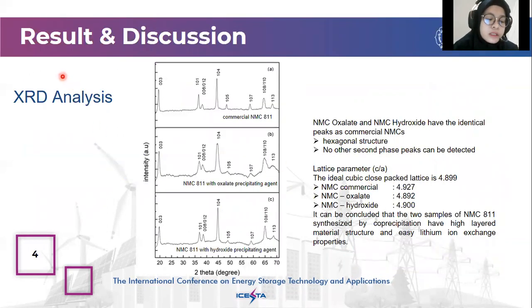Okay, from the research that has been done, the following results were obtained. First, the result of the XRD analysis. XRD analysis of NMC oxalate and NMC hydroxide compared with commercial NMC 811. The result of the XRD analysis showed that both oxalate and hydroxide NMC have peaks identical to commercial NMC 811.